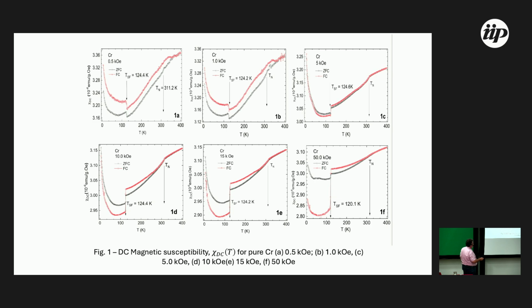For example, at 5 kOe, observe the jump in the spin flip transition. Why is there this jump? This jump is associated with the single Q state, produced when cooling down the sample and applying a magnetic field. Because below the Néel temperature, the SDW changes direction to the same direction as the applied field, producing the single Q. And in the spin flip transition there is a change from transversal behavior to longitudinal behavior.